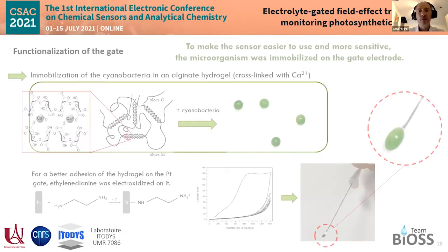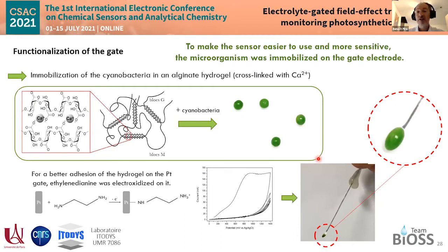So we decided to make that device more usable, let's say, by immobilizing these cyanobacteria directly on the gate of the device and not within the whole electrolytic compartment. For doing so, we immobilize the cyanobacteria in an alginate hydrogel that, so it's really nice, it makes it like a chlorophyll gum, I would say, and immobilize that on the gate by first electrografting ethylene diamine, sorry, on the platinum gate, and due to electrostatic interaction with the alginate, it helps to immobilize the hydrogel on the platinum gate.